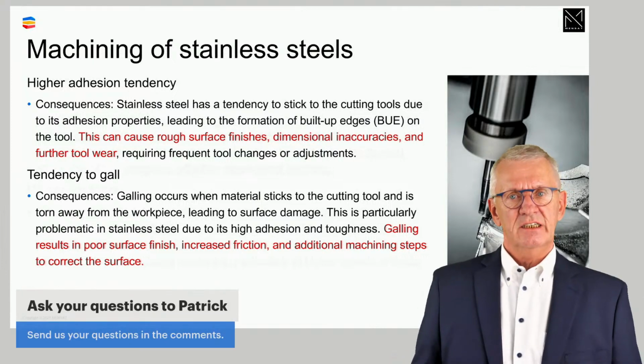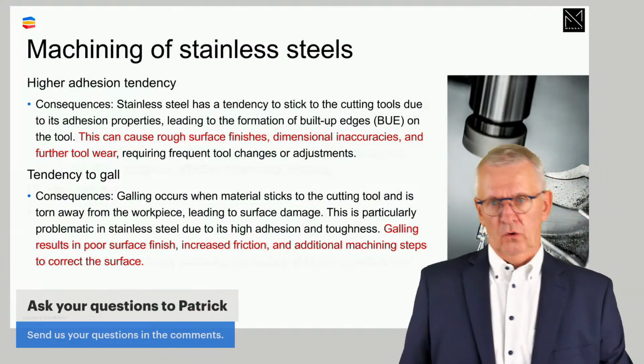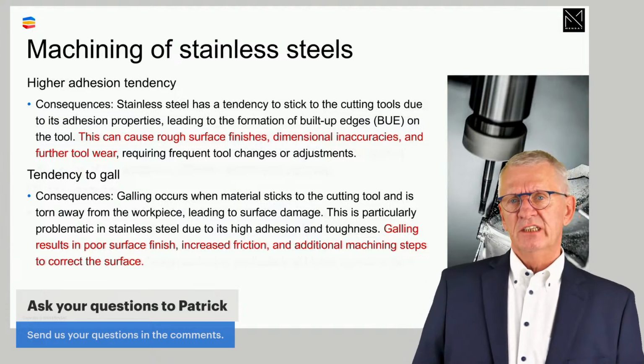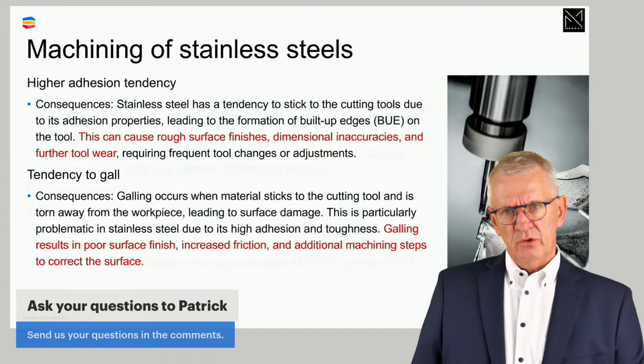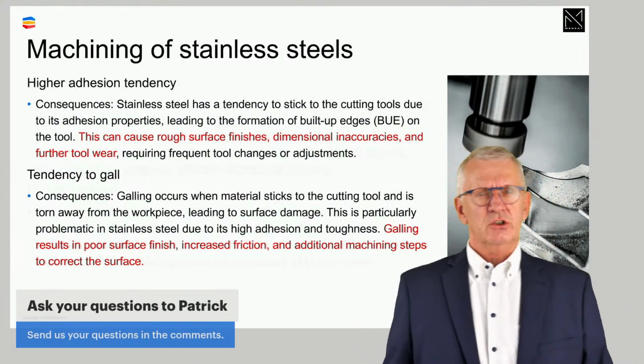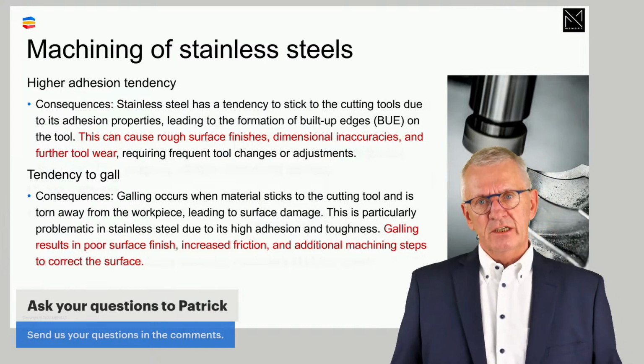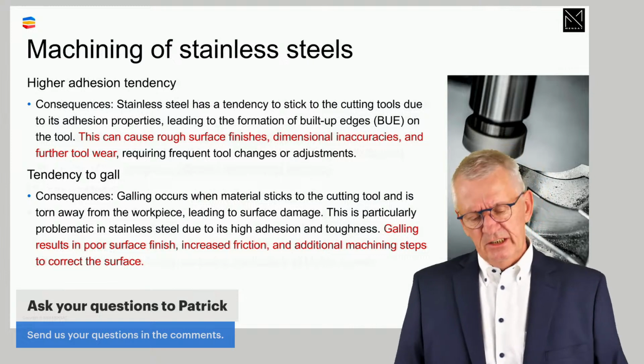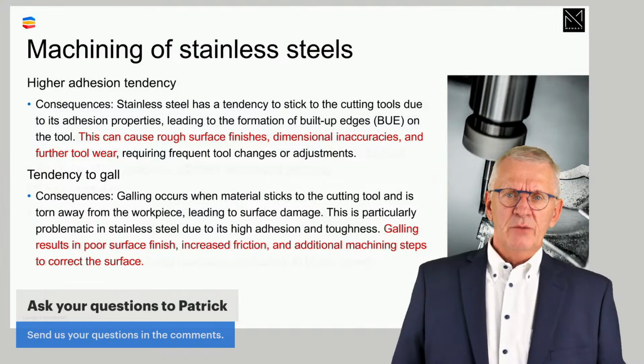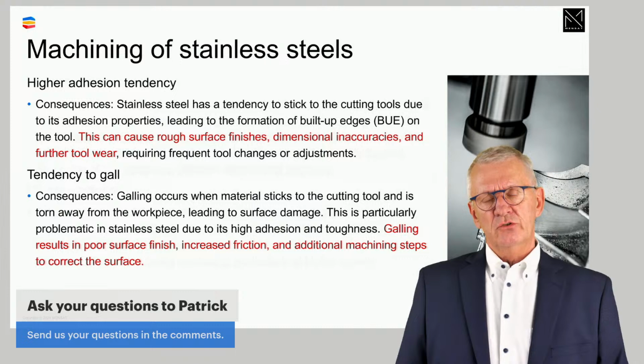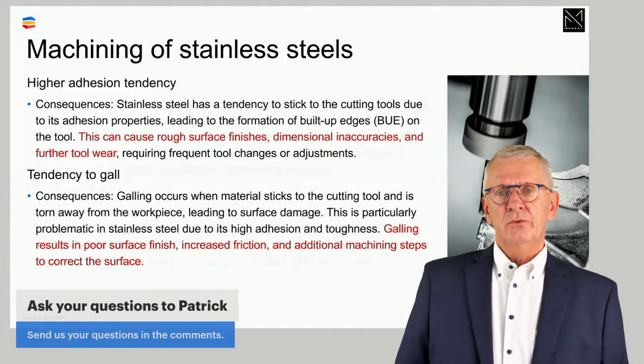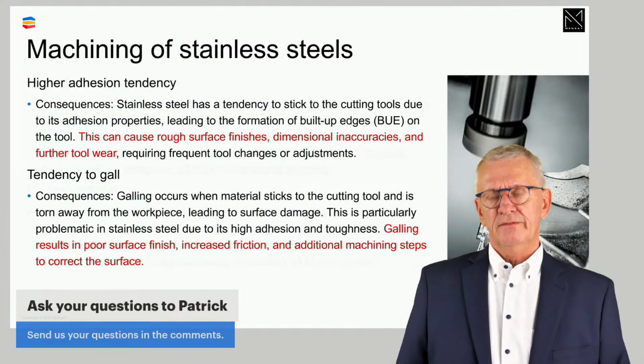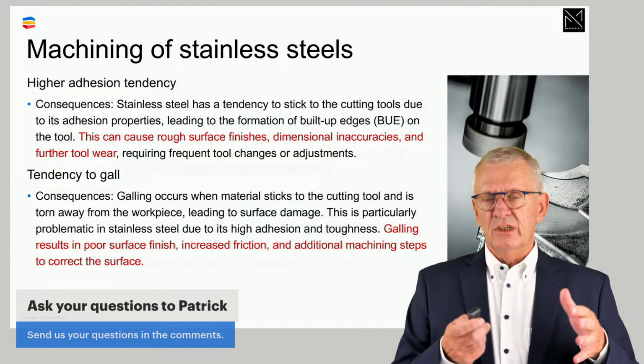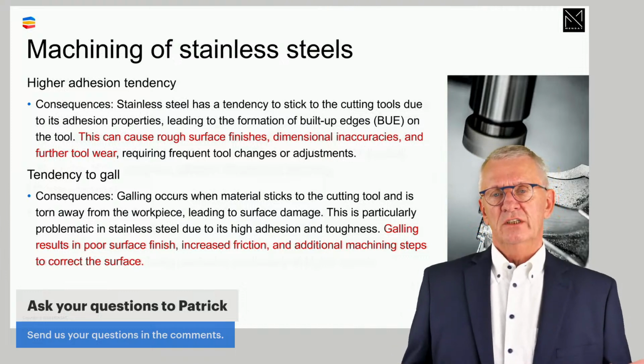Austenitic stainless steel has a higher adhesion tendency and a tendency to gall. Now, here I would like to make a difference between the two, because adhesion is when a part of the workpiece material connects to the cutting tool. It's a rather soft connection, so it's easily broken off from the cutting tool, and it could lead to chipping of a cutting edge. That's the traditional build-up edge. Tendency to gall means that in some cases the material that connects to the cutting edge connects so much that it breaks away a little bit or a part of the machined surface on the workpiece. It seems the same phenomenon, but it will give you other types of issues, because then it's going to deteriorate the quality of the machined surface of the finished workpiece, and we have to be aware of that.